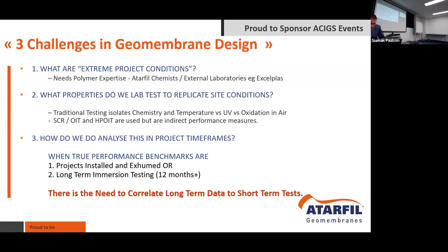The other thing is, what properties do you test in a lab to try and replicate site conditions has always been a major challenge. Traditional testing really means you're isolating chemistry and temperature versus UV versus oxidation in air and things like this. We're using parameters like stress crack, OIT and HPOIT. They're really indirect measures, but we're trying to model them quite closely to establish geomembrane life.